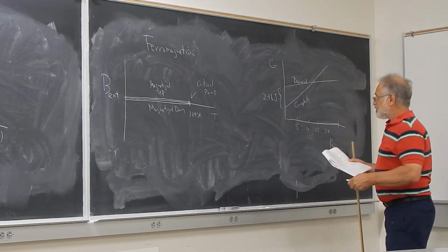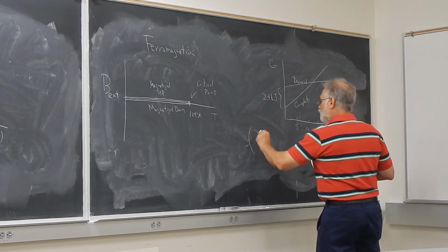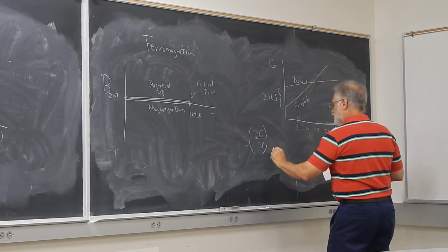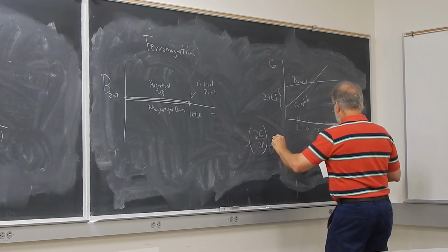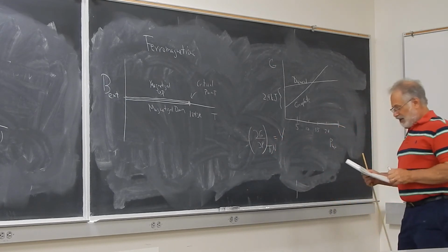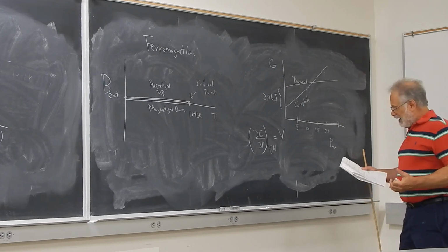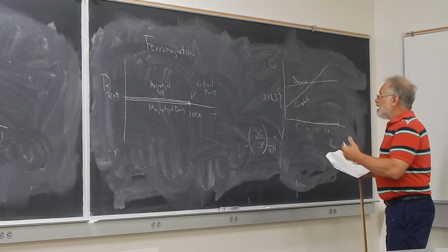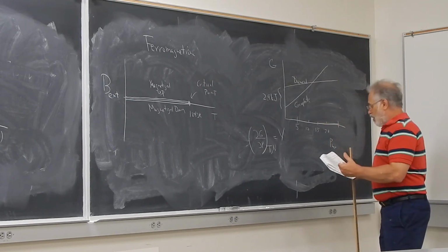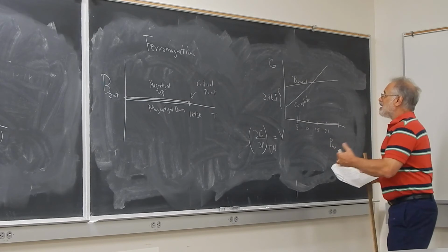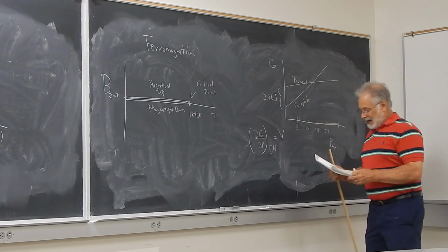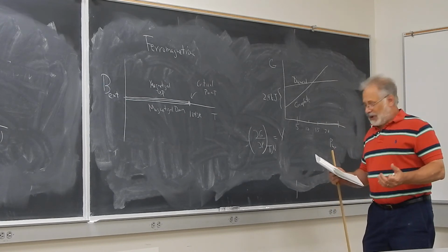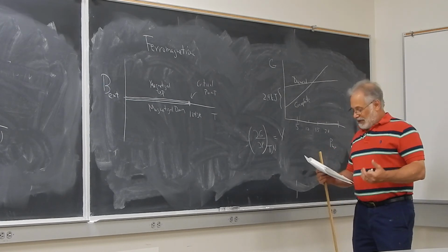At higher pressures, though, we can look at the change in the Gibbs free energy as a function of pressure for this. And of course, that gives me a volume, so it tells me that a mole of graphite has a greater volume than a mole of diamond. So therefore, the Gibbs free energy of graphite will grow more rapidly as the pressure goes up, thus making it easier to form a diamond. Once you're above 15 kilobars, 15,000 bars, diamond is more stable than graphite is.